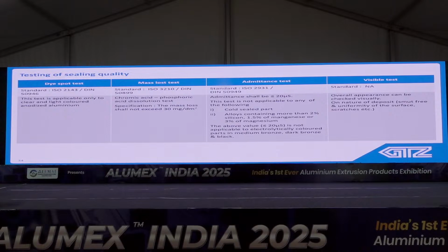Testing of sealing quality, there are mainly four tests. One is the dye spot test as per ISO 2143, the mass loss test, that is the chromic acid and phosphoric acid test, ISO 3210, then the admittance test. Aluminum oxide is inert, so it is not conducting, so the conductivity will be less, and that is the measurement of admittance. It is less than 20 microsiemens. And one is a visual test.